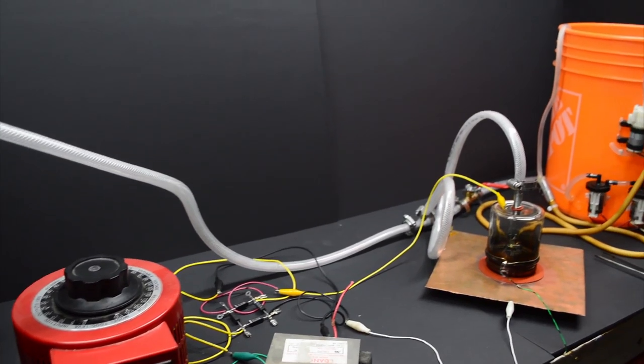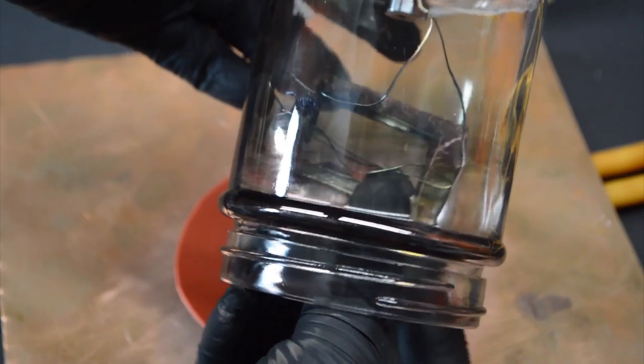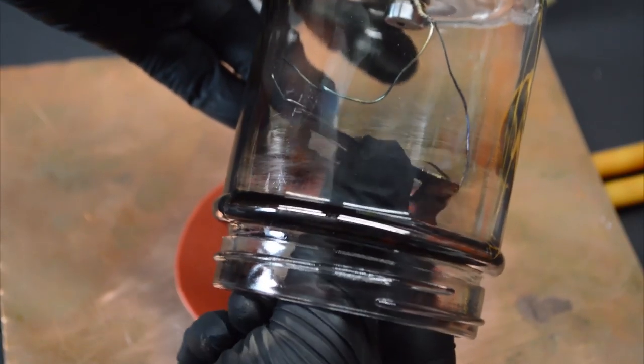Before we fire things up, the copper plate was sanded with a 600 grit or higher sandpaper, to remove any oxides or contamination. And then it's all cleaned well with acetone. The gasket is also cleaned with acetone, and then placed onto the plate. The chamber is also cleaned with acetone, as is a microscope slide, which is then loaded onto the carriage. After that, you just place the chamber onto the plate.